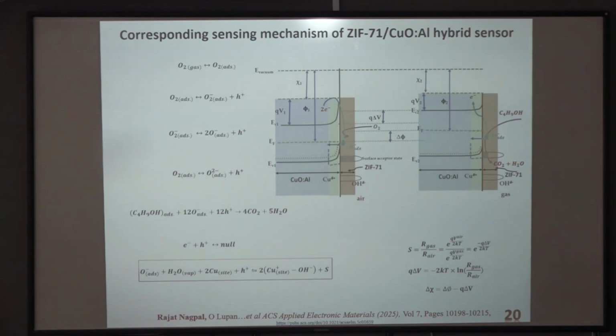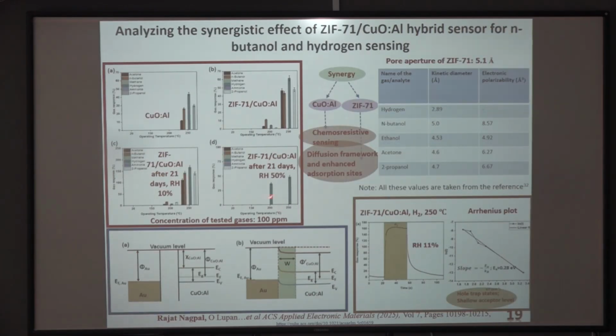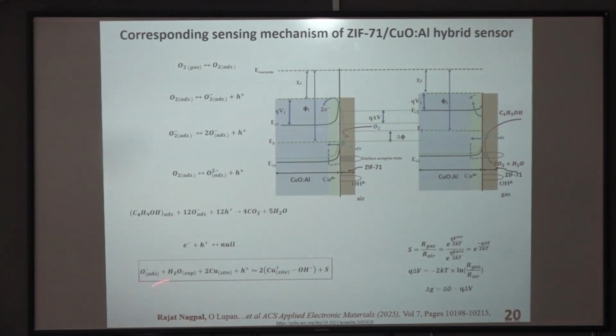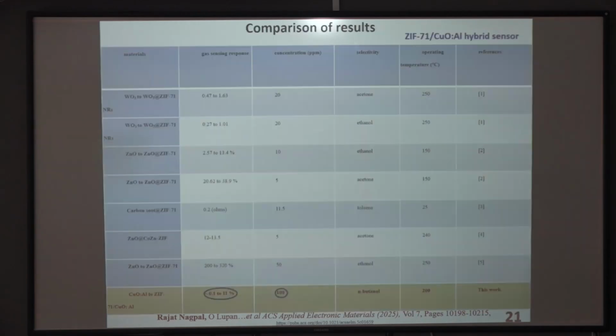Now, to understand why, in the previous slide, there is only a high sensing response for hydrogen and not for gases at high relative humidity, we can understand using this equation. At high humidity, water vapors at copper sites will make dipolar interaction with the hydroxyl group of water vapors, which will tend to decrease the oxygen concentration and give rise to a diminished sensing response for VOCs, but not for hydrogen, because hydrogen is non-polar in nature, which will have negligible impact of this.